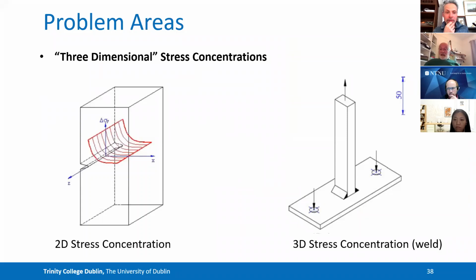And finally, a little problem we found, and we never were able to get over it, which is what we call three-dimensional stress concentrations. What I mean is, if you look at the classic notch, there's a stress concentration, but it only happens in one direction, the X direction here, right? But if you look at a problem like this, which is a welded joint, you've got a plate and you've got a bar welded to it, and you've put some welds in here, then at the corners of the welds, you have a stress gradient in two directions, right? Both directions in the plate here are directions in which, as you move away, the stress drops off very rapidly. And when we tried to use the TCD for those, we always found it was very conservative. It would give very conservative predictions.